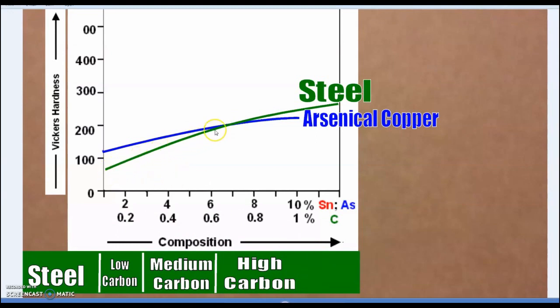So now we just have a comparison of the steel and the arsenic copper. Now up to 6% arsenic or 0.6% carbon in the steel, arsenical copper is superior on the Vickers Hardness Scale to low carbon and medium carbon steel. Medium carbon steel is used in casting, so a lot of your car parts, camshafts, these types of things have castings in them. So it's not cast iron used to make toys. They're using it, so it's still a quite good material. So high carbon steel is higher than arsenical copper on the Vickers scale.